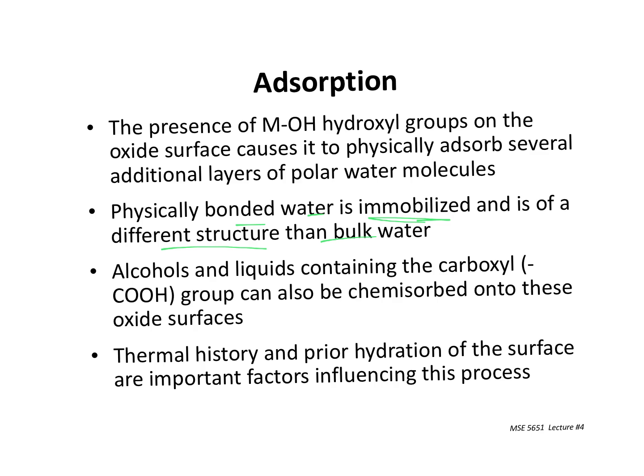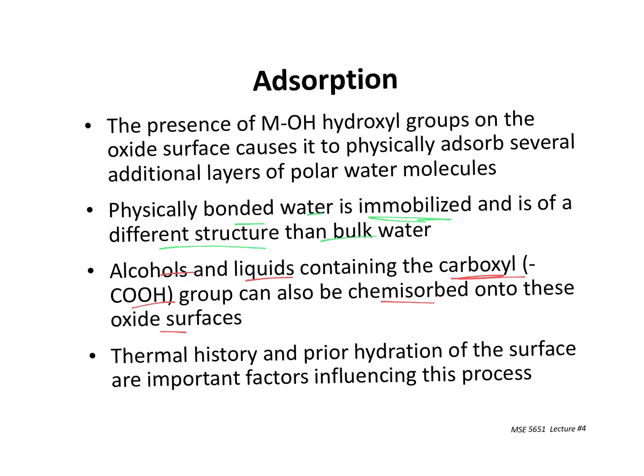We also have alcohols and liquids, especially those containing carboxylate groups, can be chemisorbed onto these oxide surfaces. And so this is sometimes a bad thing. A difference between water and alcohols and carboxyl groups is that these guys have carbon in them. All right, and so I talked a little bit earlier about how carbon changes the properties of these materials we're making. In many cases, we might want that carbon to be there because it makes carbides or properties go up. In the case of ceramics, we absolutely don't want the carbon there because we're not making any carbides in these structures. Carbon is a bad thing for ceramics for the most part. Metals, it can be a good thing.